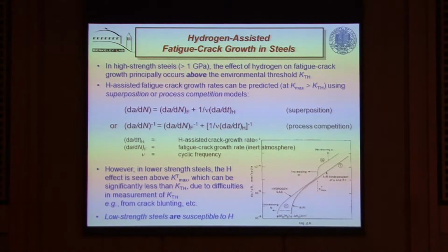So you can do this superposition in two ways. You can superpose the monotonic and the cyclic loading in series, or you can superpose it in parallel, depending on whether your two processes are simultaneous or are competitive. And I won't go into the details of this, but in high-strength steels, this is a very predictable process. This point at which you get this superposition, you can measure under sustained loading as the sustained load threshold. Very nicely cut and dry, and you can generate a good understanding.